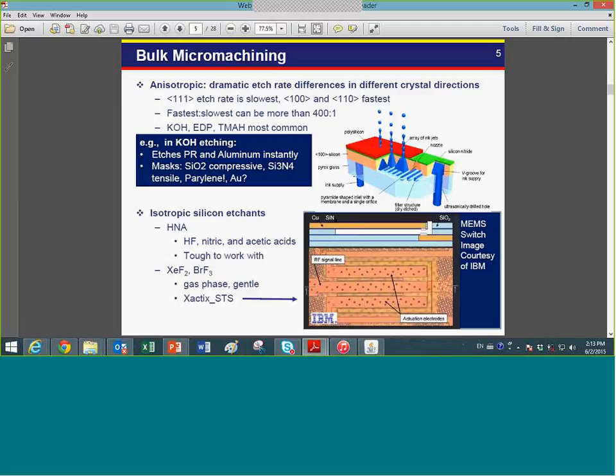Here is a typical example using bulk micromachining to make a micro printing head. And here IBM also has a technology that uses gas-phase isotropic silicon etching to remove the material underneath the copper metal to make a MEMS switch. Just to give you an idea, there is a lab at Alberta Nanofab that has this gas-phase etching. The other labs still don't have this yet.